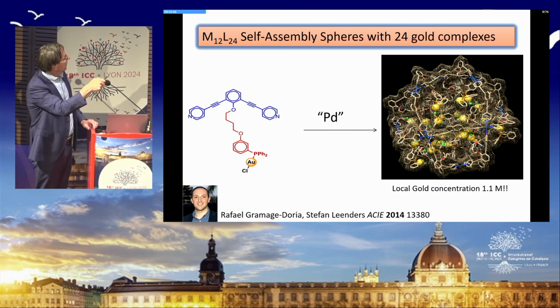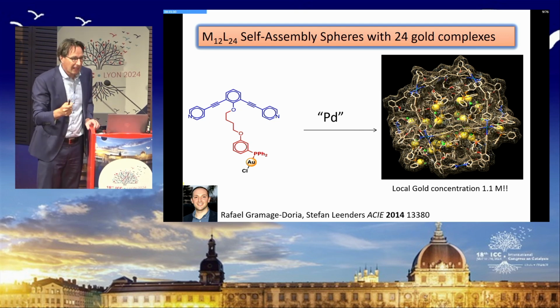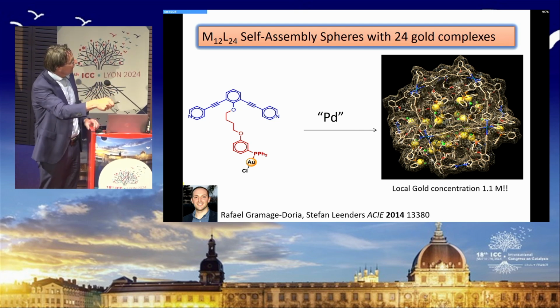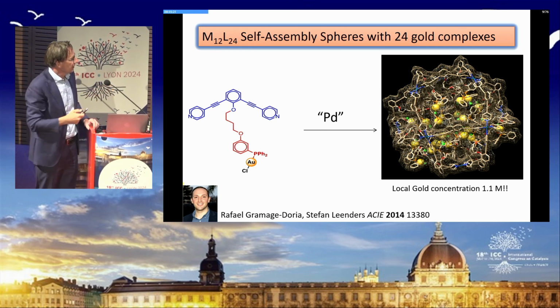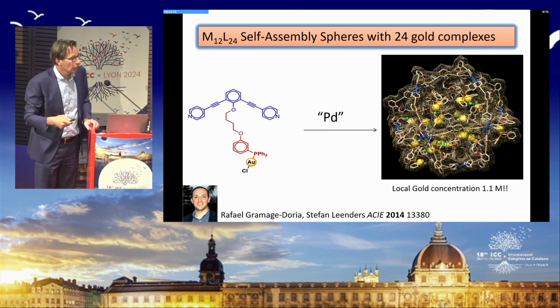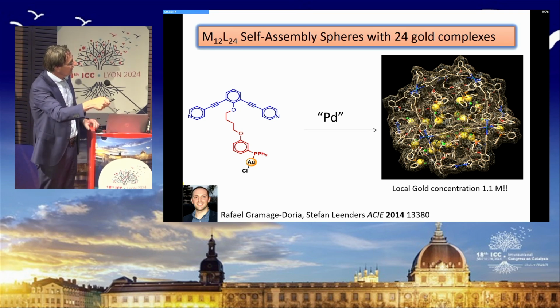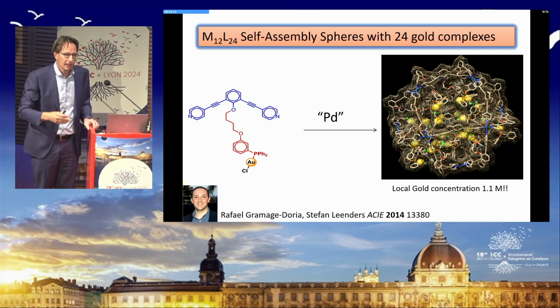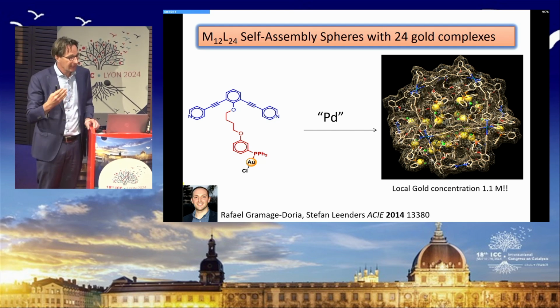He is now in Rennes, and he functionalized a ditopic building block with this gold chloride complex. And by adding the palladium precursor, you get this assembly of 24 metal complexes at the inside. And you can estimate the local gold concentration, and that is about 1.1 molar. And if you benchmark that against the concentration of toluene in pure toluene, that's about 9 molar.